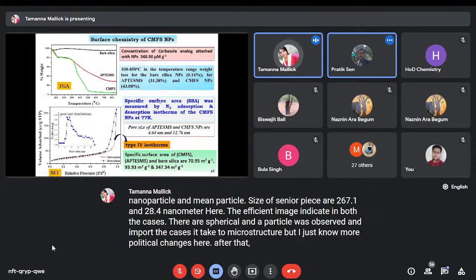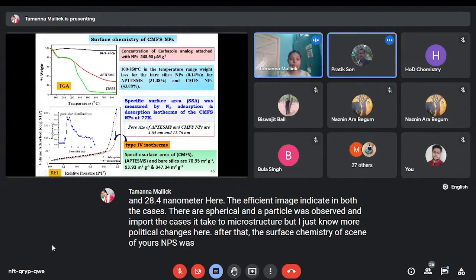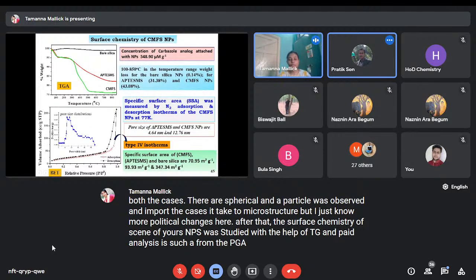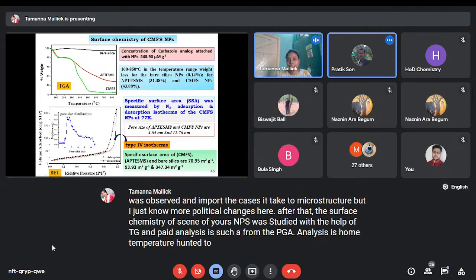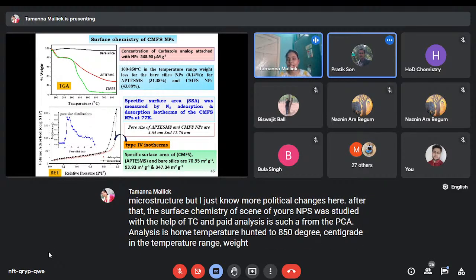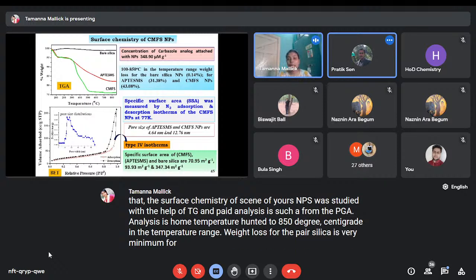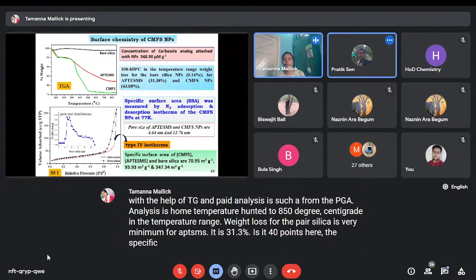After that, the surface chemistry of CMFS NPs was studied with the help of TGA and weight analysis. From the TGA analysis, in the temperature range from 100 to 850 degrees centigrade, the weight loss for the bare silica is very minimum. For APTS-MS, it is 31.38%, and for CMFS NPs it is 43.08%. Then the specific surface area was measured by N2 adsorption and desorption isotherm of the CMFS NPs at 77 Kelvin, and it follows the type 4 isotherm curve, and the specific surface area is shown here.